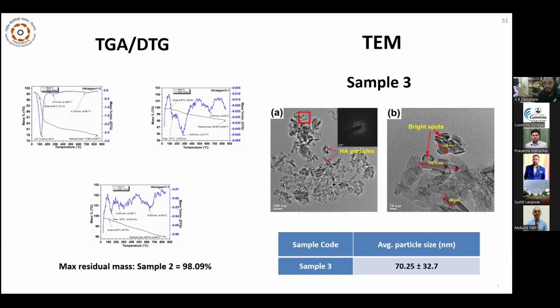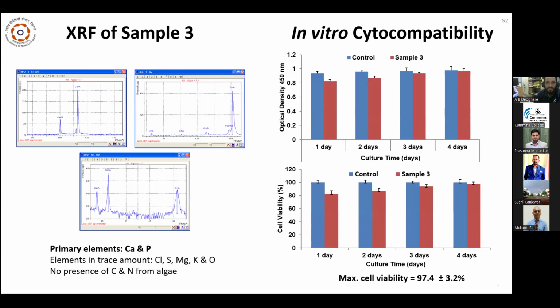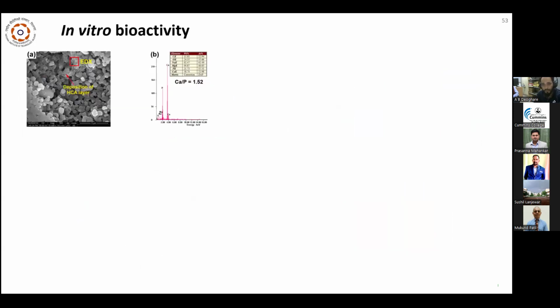Then in the case of TEM analysis, the particle size is observed, which is 70.25 ± 32.7. Then XRF analysis is performed to check the different elements, which shows calcium and phosphorus as the main primary elements. The other trace elements are also observed. An in vitro cytocompatibility test was also performed, where the maximum cell viability is 97.4 ± 3.2% on the 4th day, which shows good cytocompatibility.